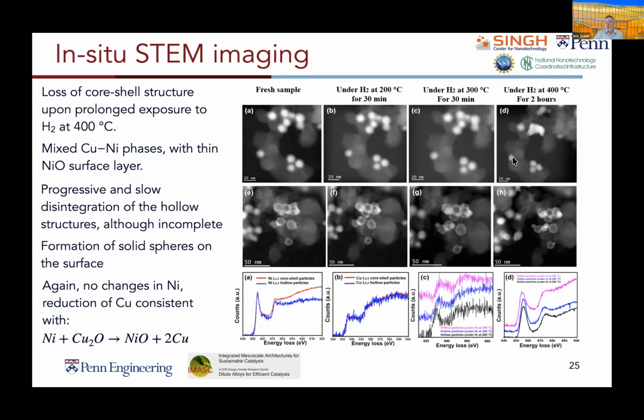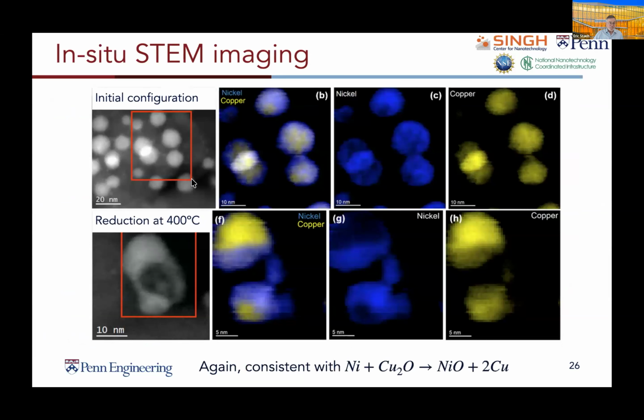And that's evident within the images as well as the electron energy loss, looking at both the copper and nickel edges from sample to sample. Furthermore, if we look at this with STEM imaging and EDS, we can see that as you go to high temperatures, we begin to have these things break apart. There's segregation of the nickel oxide on the outer surface, again, due to changes in how the hydrogen is basically reducing the copper and leading to a segregation of the nickel oxide overall.